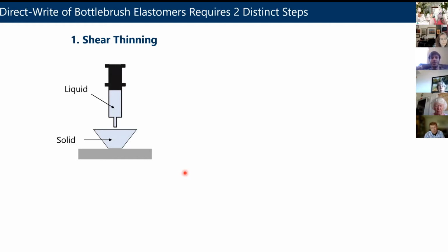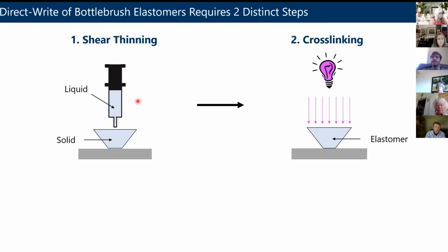You squeeze the material out of the syringe and you move the syringe around. And if you design your material depicted in blue correctly, it'll be a liquid in the syringe so you can squeeze it out, but it'll quickly solidify once it comes out of the syringe so that you can control the shape of an object in 3 dimensions as you move the syringe around. And the magic is in designing the material to have this liquid to solid transition as it comes out of the syringe. It's not straightforward to do, but if you can do it and then say, cross-link the solid, and we're going to use the same benzophenone light chemistry, then if you design your material right, you've got an elastomer.